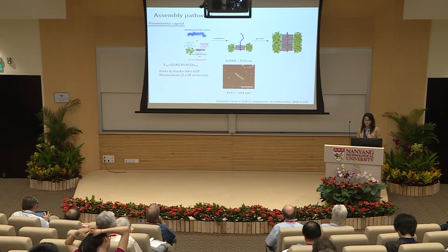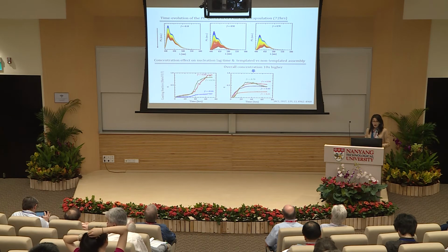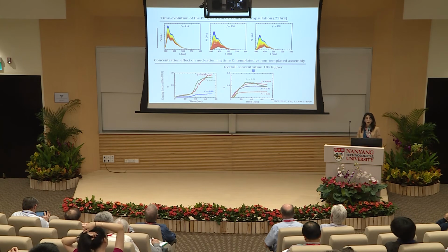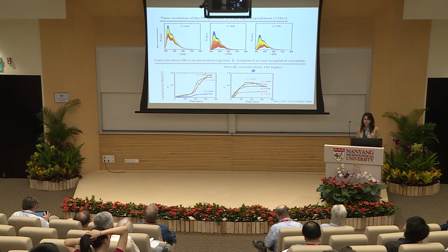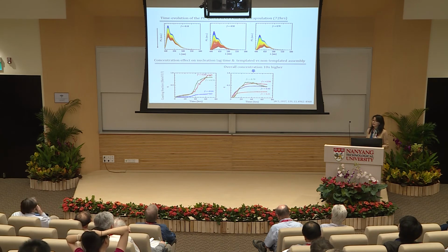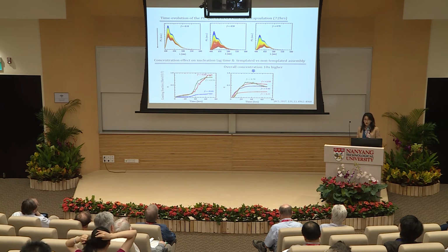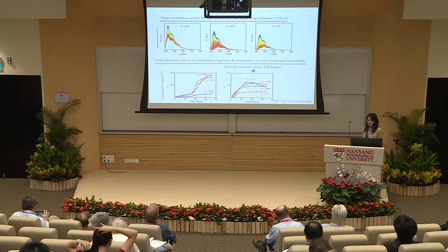with no template inside? This is what they were concerned about, and in this work, what we tried to do is find that out. How we did it is very similar to the previous one, but this time we cannot interfere with the process because it is self-assembling by itself. So we start with a very low mixing ratio, a charge stoichiometry, and an over-charge stoichiometry, so three cases. And we leave the system in fluorescence spectroscopy and measure it for a very long time.